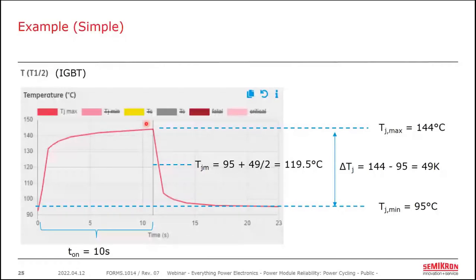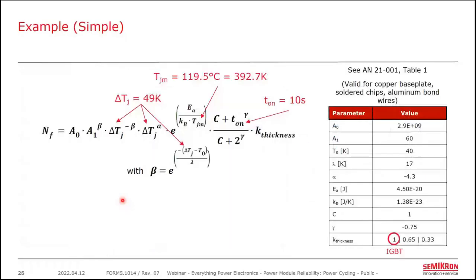And then after the overload, if we wait roughly 13 seconds or so, we get back to that starting temperature. And so from this temperature excursion, we can derive the three items we need to plug into our power cycling model, namely that delta T of 49 Kelvin, a mean junction temperature of 119.5 degrees C, and a heating time or an on time of 10 seconds. So the next step is plugging those things into the model along with all of the constants that are relevant for the module construction.